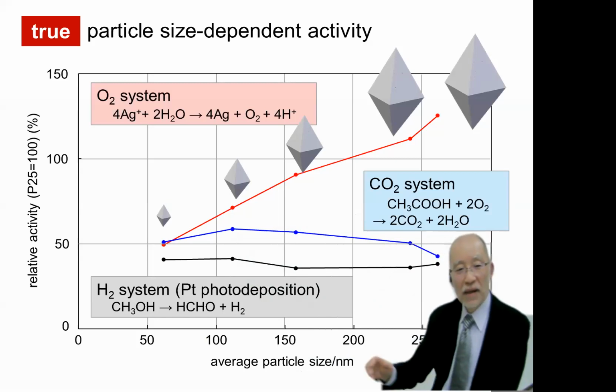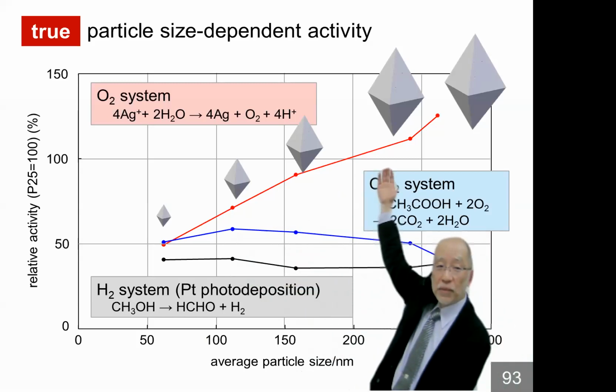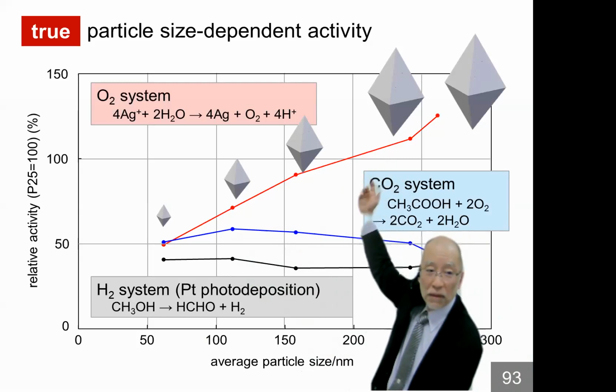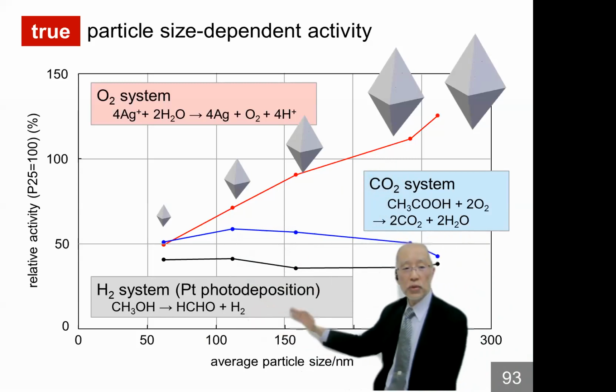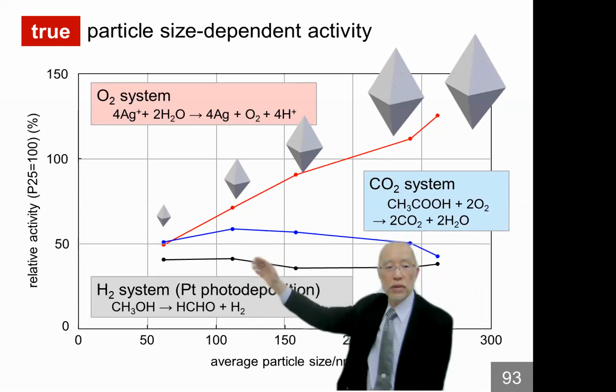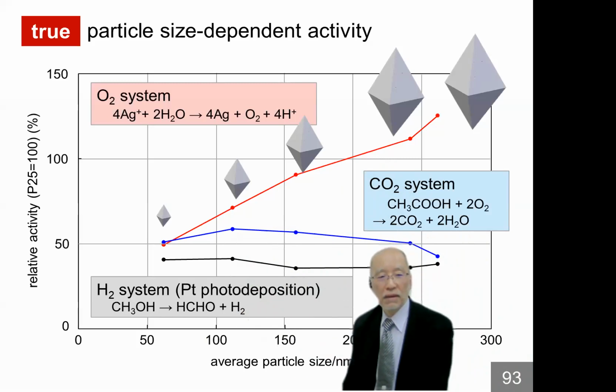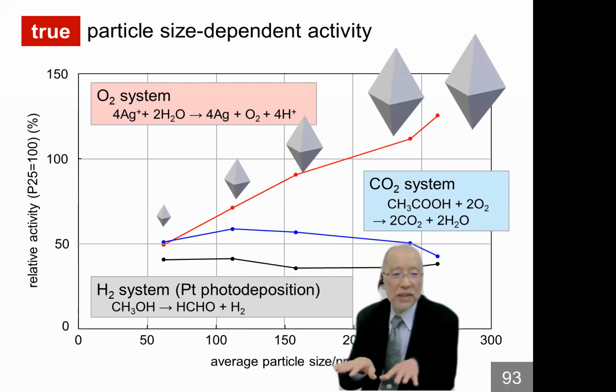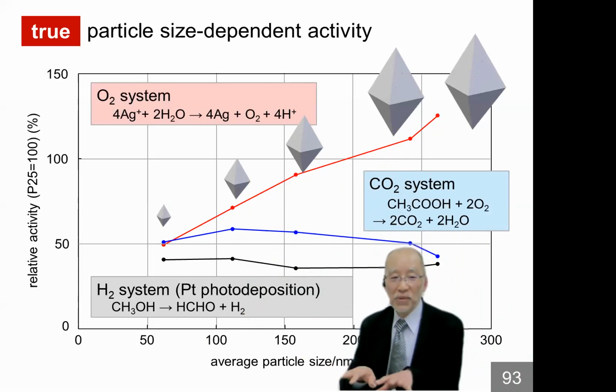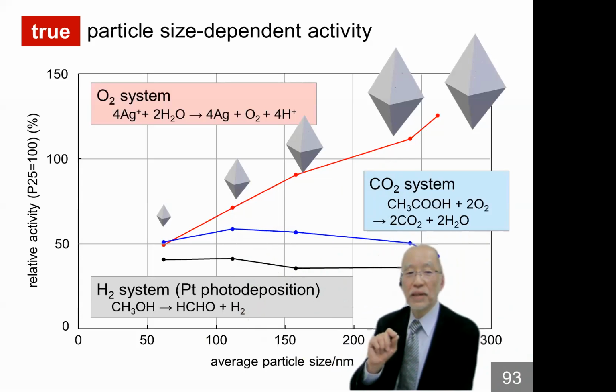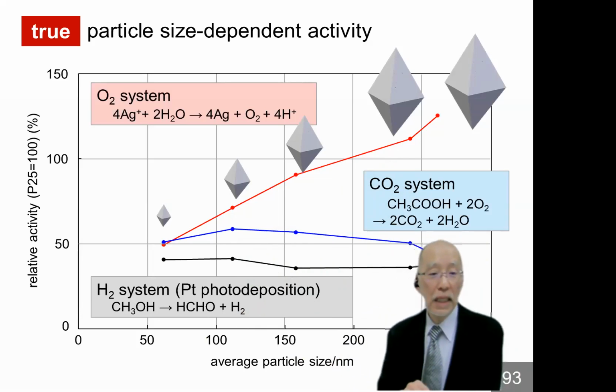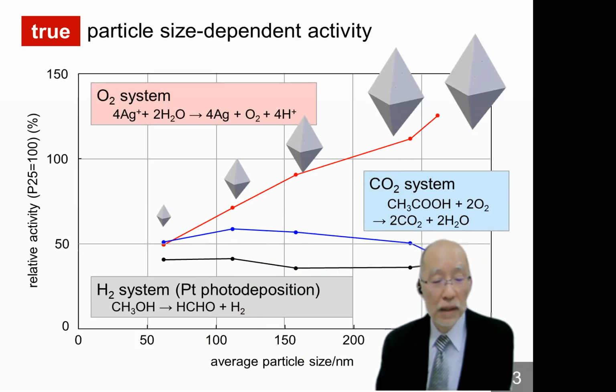That means lower specific surface area sample gives higher photocatalytic activity. And for hydrogen evolution case and carbon dioxide production case, almost constant. No particle size dependence. So this is completely different from the ordinary observation of photocatalytic activity depending on the size.